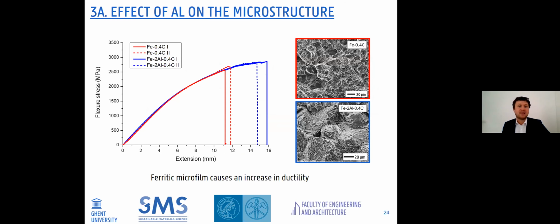What we can see then is indeed that the ferritic microfilm, because we have this ferritic microfilm when we add aluminium, shown in the blue curves, leads to an increase of ductility. So the presence of the ferritic microfilm increases the ductility. And when we use the same heat treatment for the 0.4 carbon, we also had a bainitic microfilm, and this worsened the behavior. So this clearly shows that the ferritic microfilm has a beneficial effect, and this yields, of course, opportunities to increase the ductility of very hard and brittle materials by inventive grain boundary engineering.